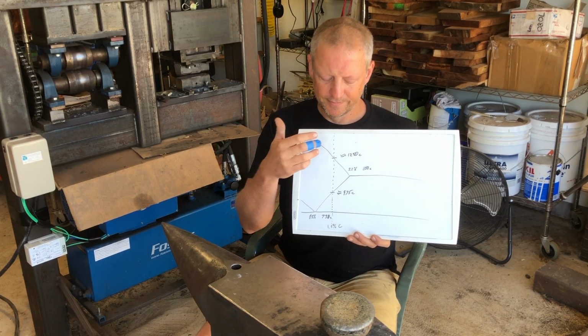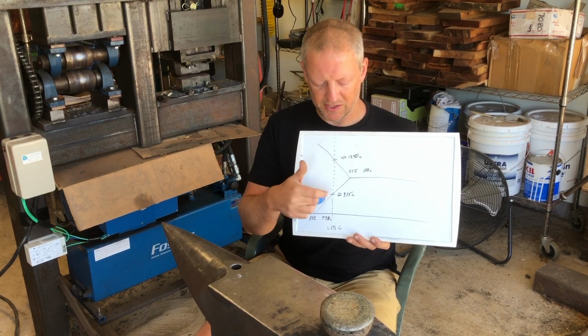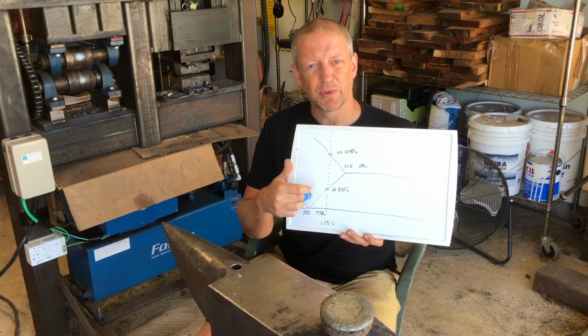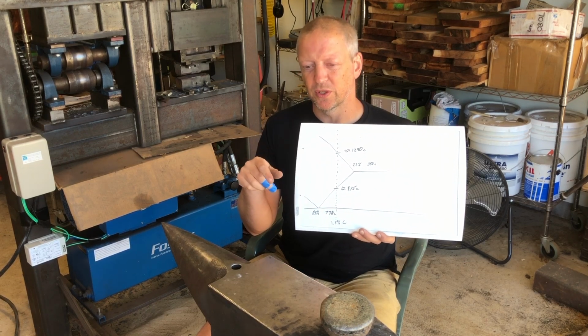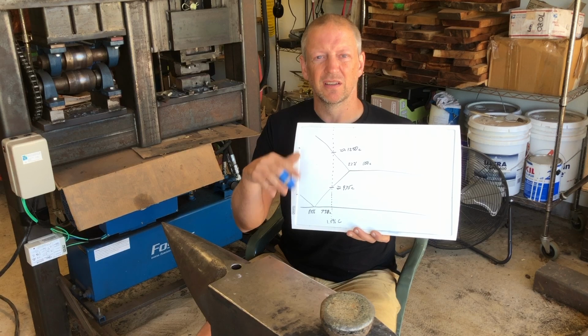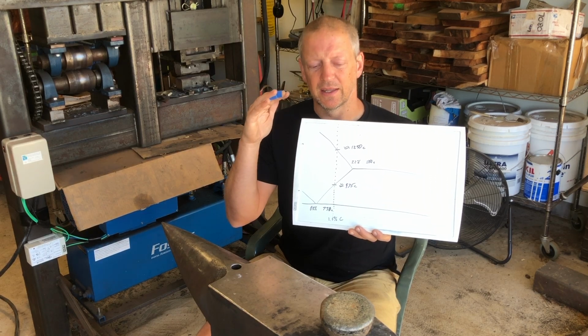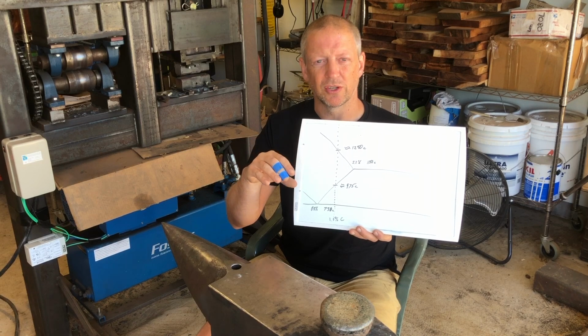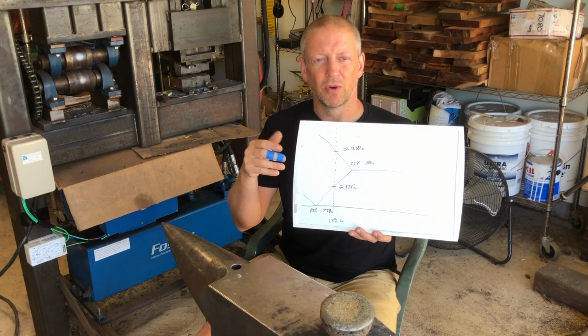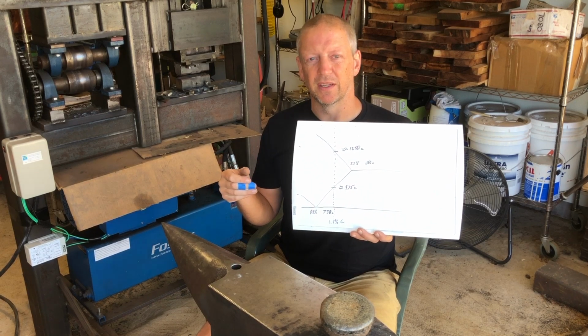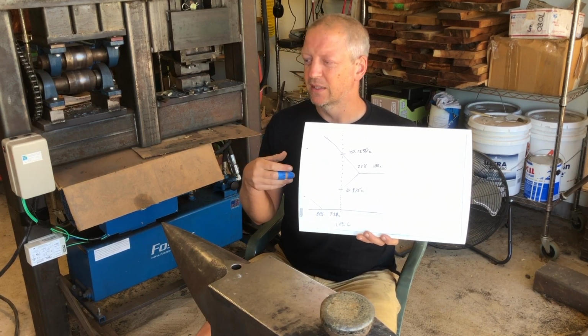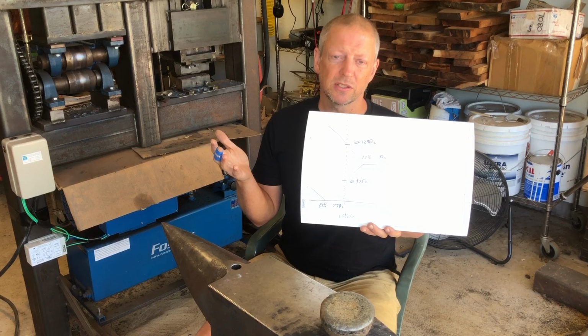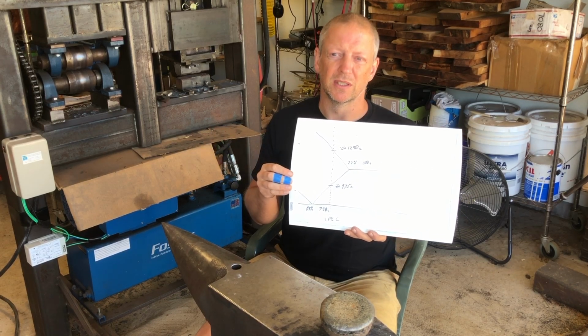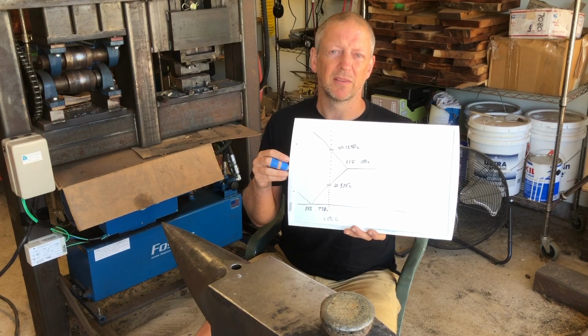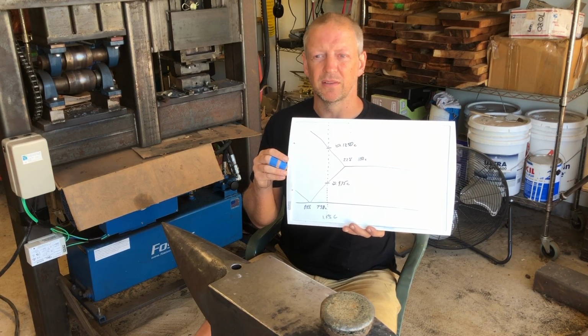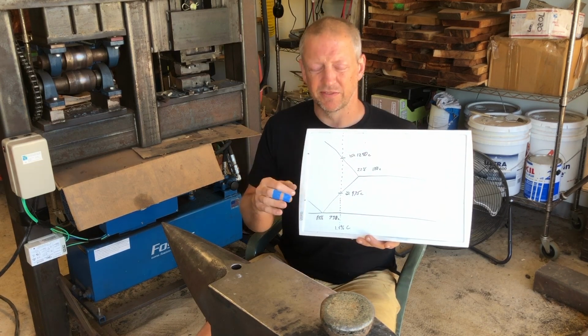So you really want to make sure, if you are going to be sitting in that temperature range, right around the ACM, that you have first consolidated your ingot to close up that initial porous structure, and therefore avoid getting a huge amount of graphite in your blade. Graphite has a lot of great characteristics, but not for swords. Pencil lead is graphite. That is not something you'd want in your sword. First piece of advice there.